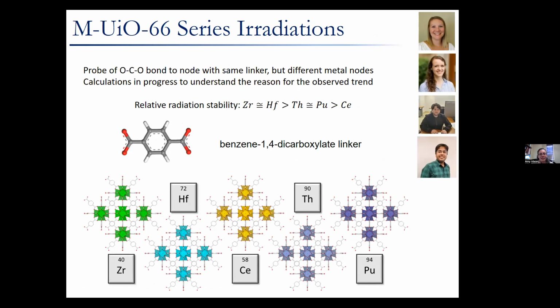Along those lines, I can say that we've completed all of the characterization and irradiation of an entire series of MUiO-66. I showed you before just zirconium where we were changing what the linker is. In this case, we're keeping the MOF the same and changing what the metal center is, because we're able to synthesize this MOF with most tetravalent metals. So we're able to look at zirconium, hafnium, cerium, thorium, and plutonium, and therefore get an understanding of d block versus f block and 4f versus 5f.